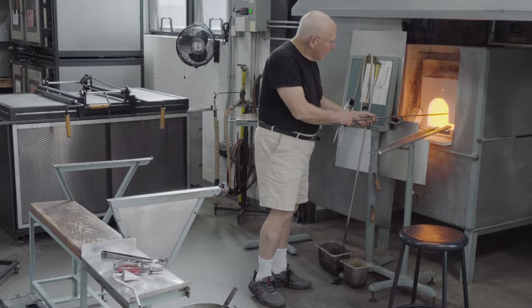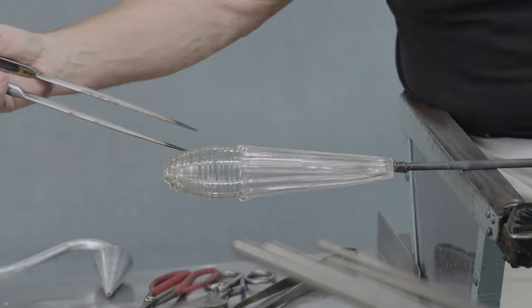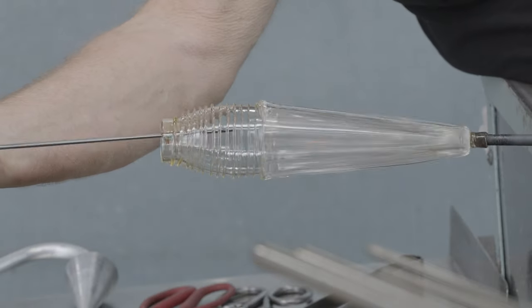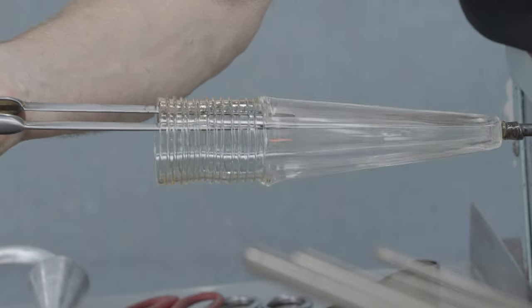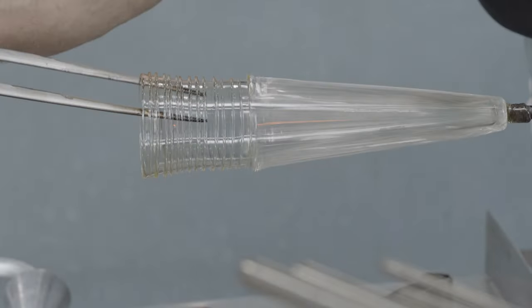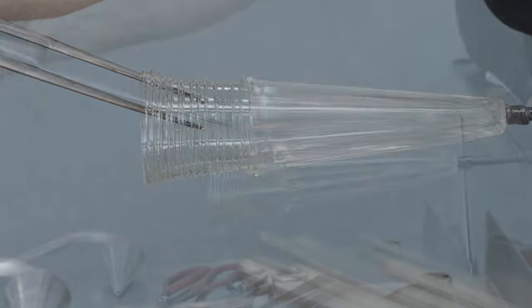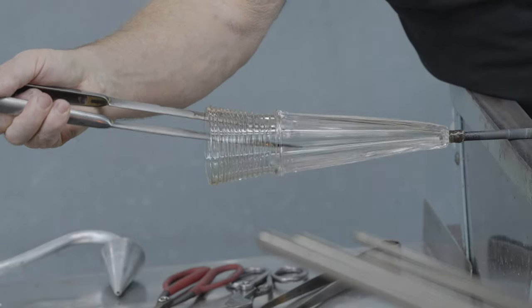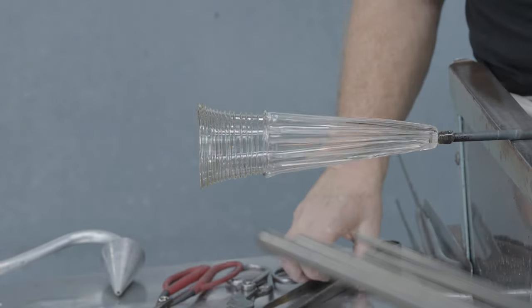This is the longest reheating in glassblowing, the initial reheat after the transfer to the punty. The glass is softened, and the jack is used to dilate the hole and to shape the sides. And the rim is given its final flare.